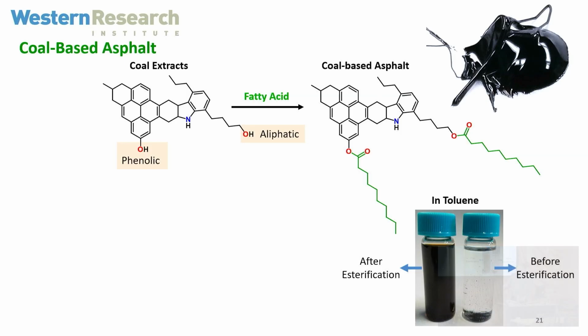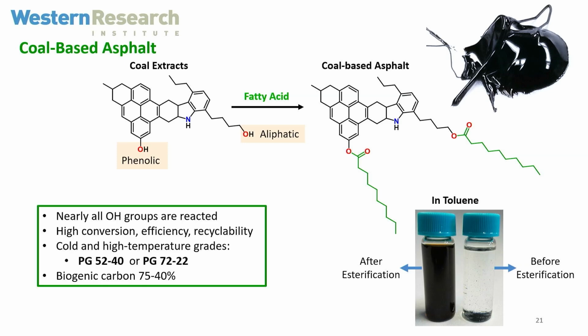Also, this is just showing you the material before and after the reaction in toluene. Before doing this reaction with the fatty acids, it's not soluble in toluene. Afterwards, completely soluble. So we really changed the properties of this material. And asphalt binder itself is completely soluble in toluene, so that's good. We react almost all the OH groups on our coal molecules. It's a very high conversion, this process. We can recycle any extra solvents. And more importantly, we make the right grade of materials that we want.